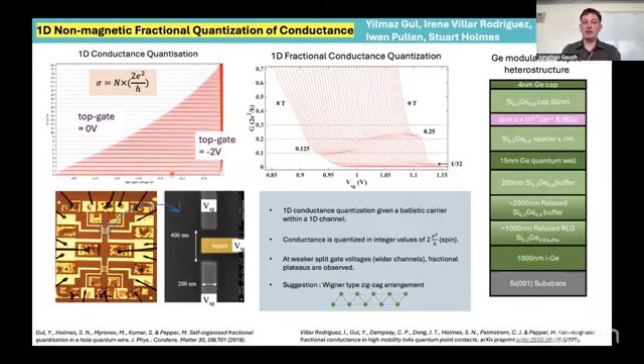It's been known for a long time that you can observe this quantization in your measured conductance due to the number of conduction channels that you can fit into this smaller 1D wire. Quantization in units of typically e²/h or 2e²/h has been known for a long time. The 2 comes from the spin degeneracy of your channels. However, what was noticed 5-6 years ago was that as you relax the channel width, you observe these fractional plateaus, say 0.25 in this case.